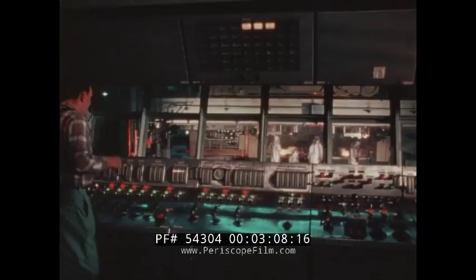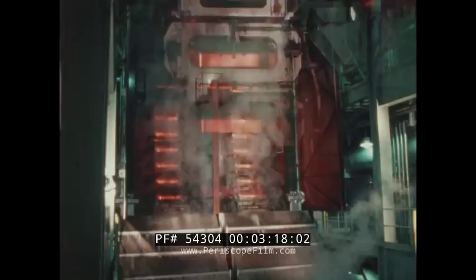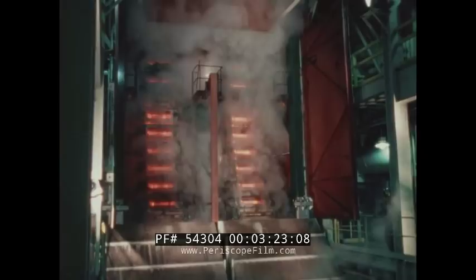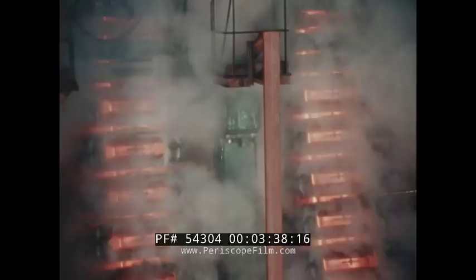The bloom, measuring as much as 10 by 23 inches, descends through multiple sets of non-driven guide rolls to a spray chamber, where hundreds of water sprays cool the steel on all four sides. The sprays are controlled by the computer system, which considers the casting speed, grade of steel, spray water temperature, and bloom temperature. The spray is regulated in five separate zones to create the desired solidification patterns, further assuring good surface and internal quality that pays off in better drawing characteristics and non-porous plating surfaces.